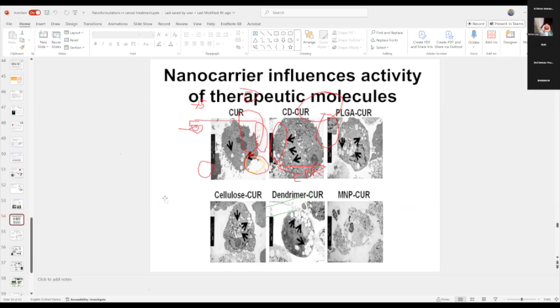Okay, so I listed a number of different formulations, but how do we pick a nano formulation for drug delivery, or how best can you employ it in cancer therapeutics? What we did here, simply, we took a natural molecule called curcumin, and we formulated the same molecule with cyclodextrin assemblies, PLGA nanoparticles, cellulose nanocrystals, dendrimer based nanomaterials, and then magnetic nanoparticles that contain this curcumin molecule. So we made all these and then we put them on the prostate cancer cells.